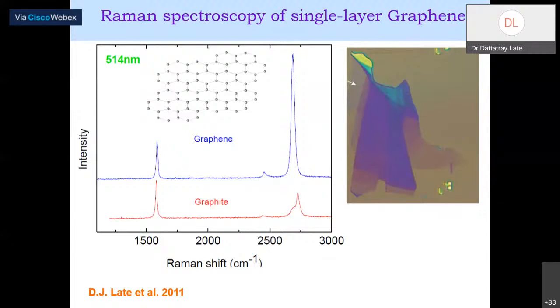So you can characterize this graphene. You can see these are two spectra: the spectra of graphite, maybe multi-layer graphene, and graphene, which is a single-layer graphene sample. Here you can see just the left corner of this optical image, exactly where I have kept the arrow. This is the graphene spectra, maybe a monolayer of graphene, and these are multi-layer graphene. How can you see this? Can you see the distinguishing characteristic feature? I can see many features in these two particular spectra.